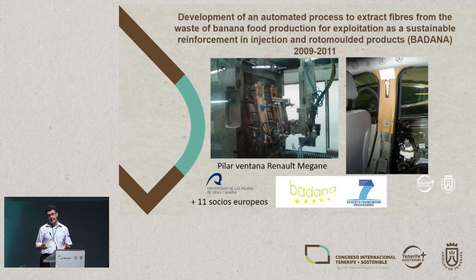It's injected plastics, as we can see on the right. We tested this against all the standards required by the automotive industry, and interestingly it's one of the natural fibres that passed all the tests where glass fibre couldn't. One problem with natural fibres is the smell when they're processed — in this case it's an injection process so we increase the temperature considerably, which can produce odours. There is a very strict standard for the smell inside a vehicle. Banana fibre is the only natural fibre that passed this test, whereas linen and abaca hadn't managed to.